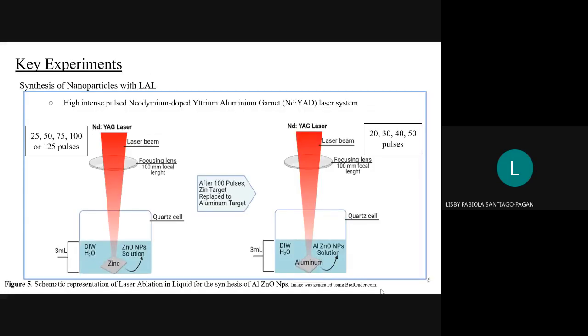The laser system used a neodymium-doped yttrium aluminum garnet, providing pulses of 1064 nanometers, and the reaction was performed at room temperature, assembled as I illustrate here in the figure. The laser beam was concentrated towards the zinc target with a different number of pulses. Once the beam interacted with the zinc surface, ablation of the material was achieved, and the nanoparticles were acquired as a suspension. Finally, after 100 pulses, the zinc surface was replaced with an aluminum surface so that the zinc oxide nanoparticles could be doped.